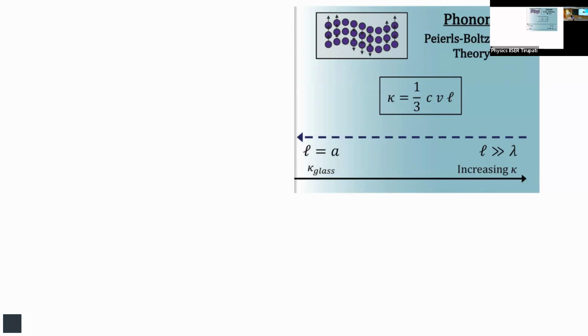The mean-free path is the distance over which a phonon goes before it gets scattered. If the mean-free path is very large, I'll have high thermal conductivity. I want to make the mean-free path smaller and smaller. What is the smallest distance that I can think of to scatter a phonon? It cannot be smaller than the interatomic distance, because it has to be another atom that scatters the phonon. So the smallest mean-free path of a phonon can be the interatomic distance.